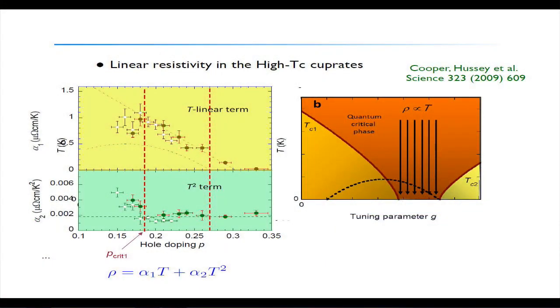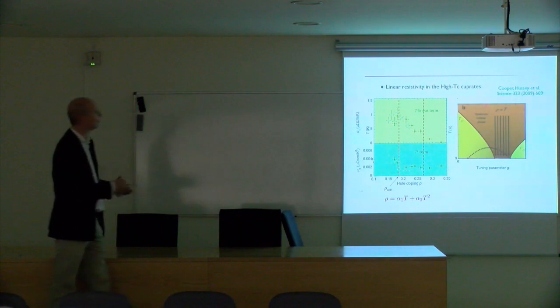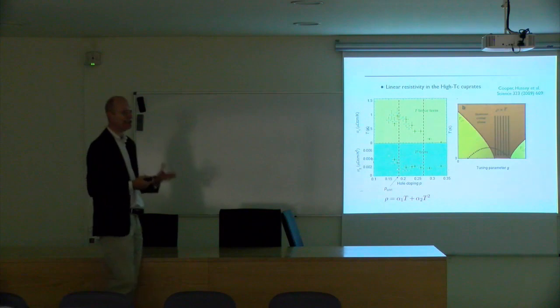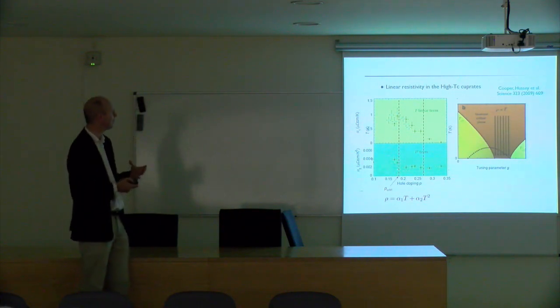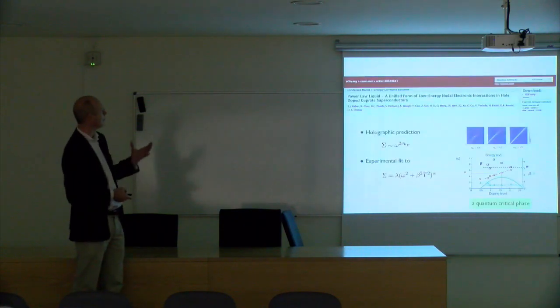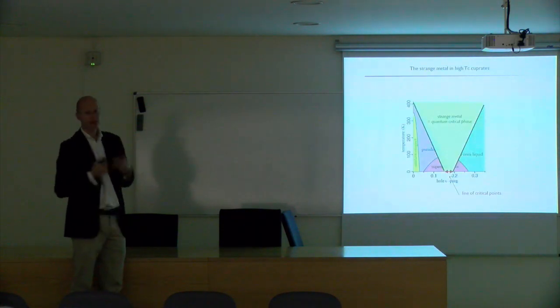and it's certainly not something that you see very often in condensed matter physics. But oddly enough, if you do very high precision measurements on the linear resistivity, so a completely different experiment, you measure the resistivity as a function of temperature, you also find that this linear in temperature resistivity seems to originate in a regime, in a band of doping, not in a single point. So there are two indications that this is actually a rather interesting system where you have a line of critical points rather than a single critical point. But let's go back to this experiment where they showed this.